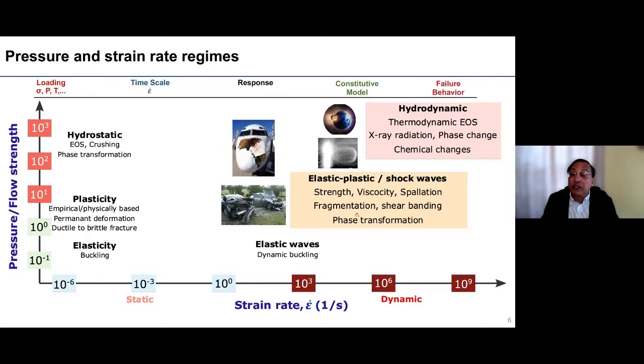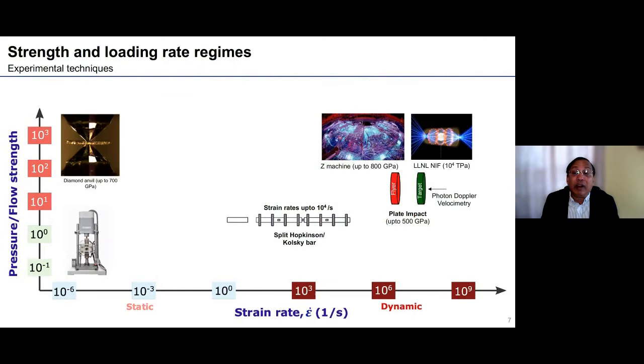So you want to understand this whole range of phenomena, and one of the things which governs phenomena such as fragmentation and failure is the strength of the material, and this is something we are interested in understanding at high pressures. Obviously we have numerous techniques to address these problems. Of course, at low strain rates, one has hydraulic or servo-hydraulic machines or screw-driven machines to understand the strength behavior of the materials, yield stress and flow behavior, which is very well characterized. Another technique used for high pressures is the so-called diamond anvil cell technique.